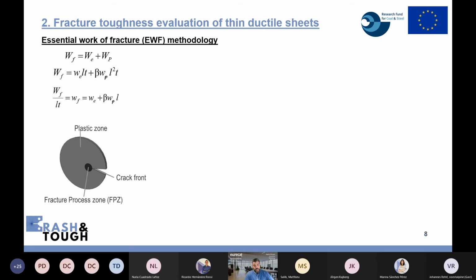One of the methodologies that we have worked with in the last years is the essential work of fracture. We have seen that this is one of the most suitable methodologies to evaluate the fracture resistance or the crack propagation resistance of thin metallic sheets, not only of advanced high-strength steels, but also high-strength aluminum alloys and all kinds of ductile sheets.